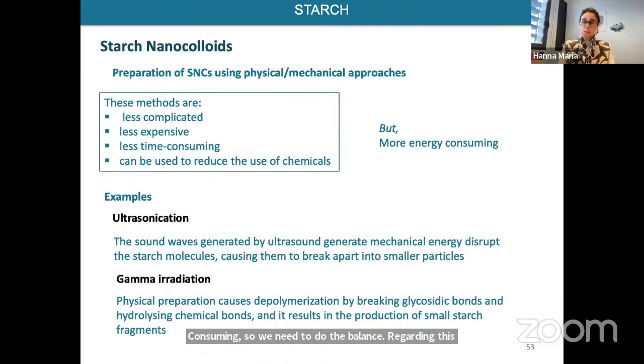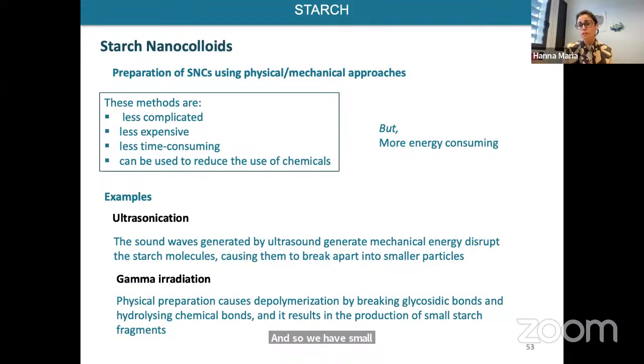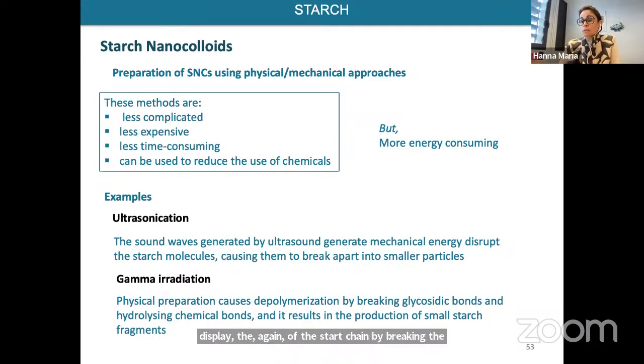Okay, so I have two examples here. The ultrasonication, so you know this kind of method. The ultrasound generates mechanical energy, and it will disrupt the linkages between the starch molecules, and so we have small particles of starch. And if we use gamma irradiation, for instance, in this case it's again the depolymerization of the starch chain by breaking the glycosidic bonds. And in this case, we also can have small fragments of starch.